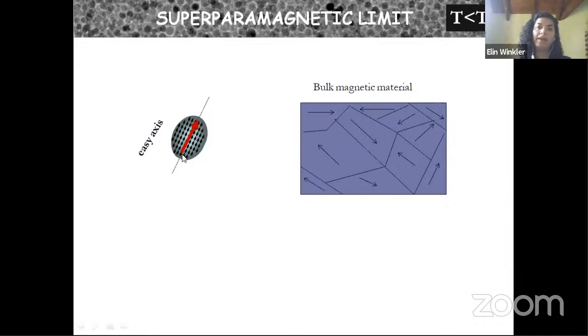Now, along which direction does that magnetic moment align? Well, in principle, the magnetic moment could be aligned along any direction if the material is isotropic, but usually the material presents some kind of anisotropy that could have different origins. For example, there could be a shape anisotropy that determines a specific direction, also a magnetocrystalline anisotropy due to the particular structure of the material. Also the stress could generate some specific direction. So these energies determine a preferential direction where the magnetic moments are aligned.